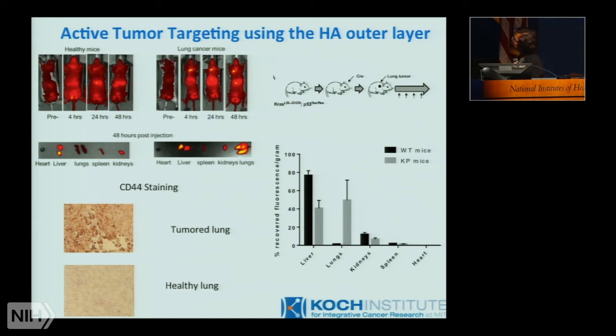We looked at the active targeting of our nanoparticle in healthy mice. So here we do a tail vein injection, and we see that the nanoparticle resides throughout the mouse's body, but there's no particular localization, versus mice which exhibited these lung cancers, these mini tumors. We saw that over a period of time, we got a large accumulation of the nanoparticles in the tumored lungs.